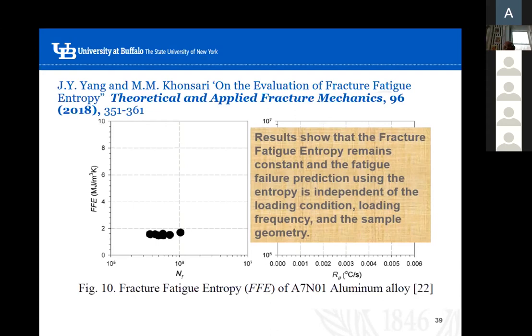It's not a function of the geometry. Okay, so when you do high cycle fatigue, and then you are comparing stress strain diagrams, and you say the number of cycles as a function of stress is dependent on the size of the sample, right? About the fracture at the end of the life of the high cycle fatigue, it is probably a strong function of the size. If we take a smaller size, take a bigger size, the life we are getting from the test data is quite different. It's known. We know size is playing a lot of role. Yes, thank you. Okay, but what are you comparing?